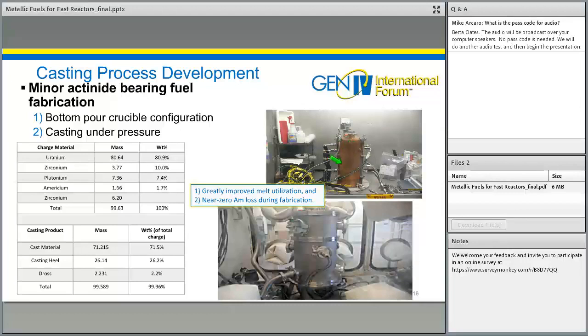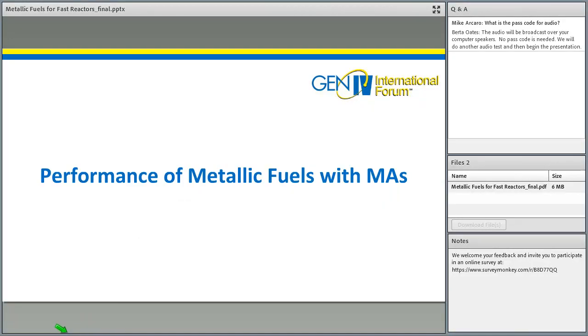And we proved out a lot of the ideas we had in a hood, and then we went to the next generation of furnace, which was installed in a glove box, and validated much of what we'd learned using surrogate materials in a glove box using actual materials, actual actinide materials. So casting with uranium, plutonium, americium. And what we learned is these changes to the approach did two things for us. One, they did greatly improve melt utilization by being able to drain the entire crucible in every casting run. And they really did drive the americium loss during each fabrication pass down to essentially zero. So that's what we've done in the area of fabrication to address issues.